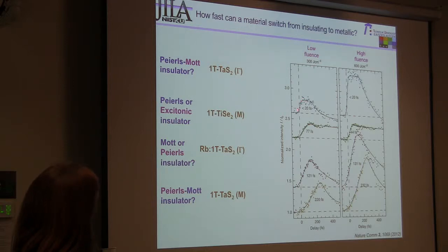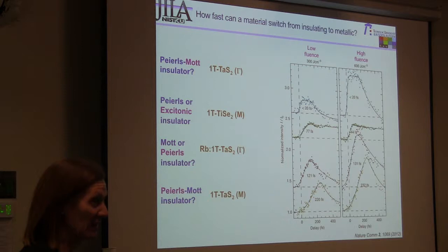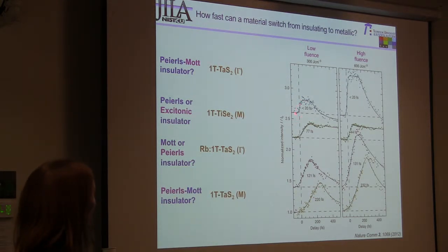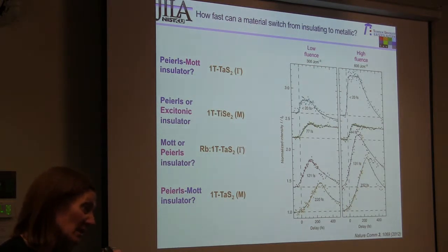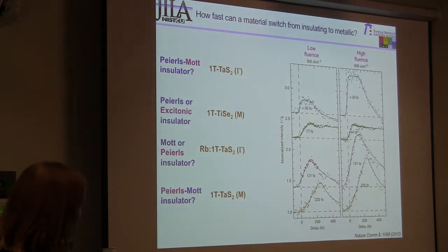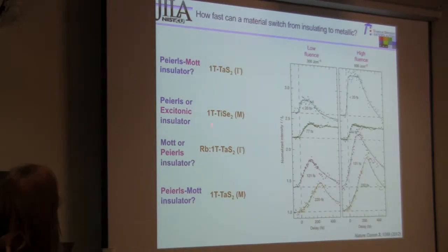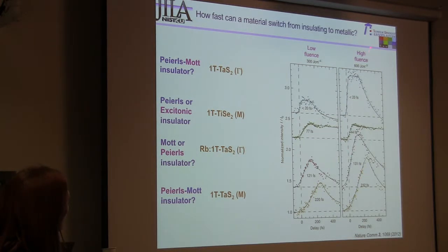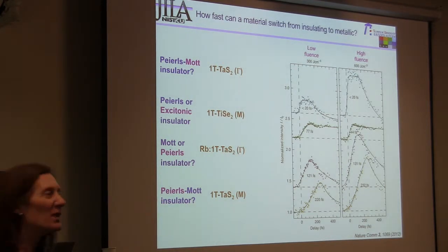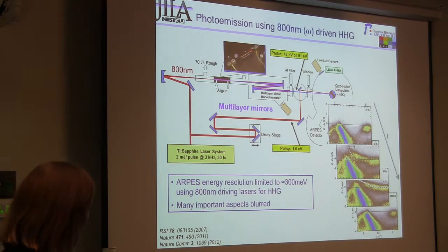So the idea is, depending on how quickly the material responds, you know if it's dominated by electron-electron interactions or electron-phonon interactions. If the charge density wave order melts in less than 20 femtoseconds, then since an LO phonon period is about 100 femtoseconds, that tells you that this must be Mott or excitonic. And if, as you change the laser intensity, the time scale doesn't change, then you know it has to be Mott. Whereas if you increase the laser intensity and the charge density wave melting time goes from 77 to 35 femtoseconds, that's indicating that there's electron screening effects, and that tells you it must be an excitonic state. And if it's long and doesn't change as you change the laser fluence, then you can say it's predominantly Peierls. So this is a very simple classification, and I could say more, but maybe we'll keep it for the discussions. Margaret?